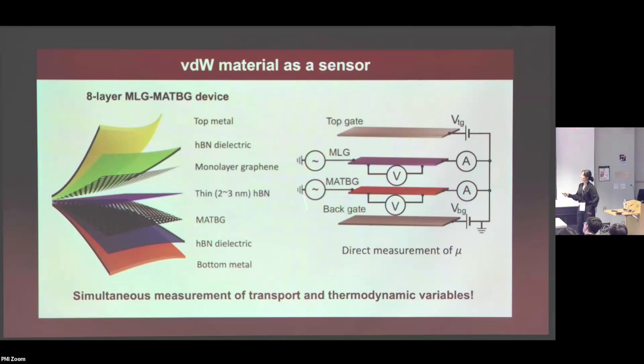In this regime, if you measure the transport of both of the layers, a chemical potential change in the magic angle twisted graphene will be reflected in the phase space map of the monolayer graphene. So if you can track how your Dirac point moves in the phase space, you can directly convert that into the chemical potential of the magic angle twisted graphene, and that's just using the screening properties of the materials. If you have a metal, it will be screening a lot. If you have an insulator, it will be screening less. The effect of the backgate.